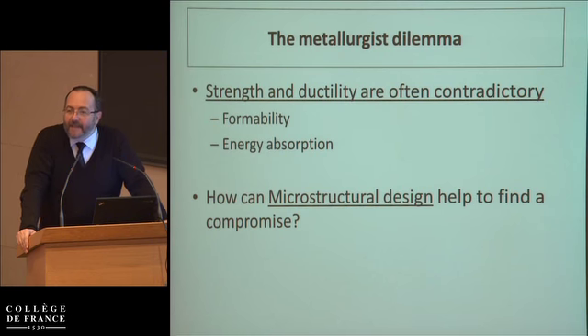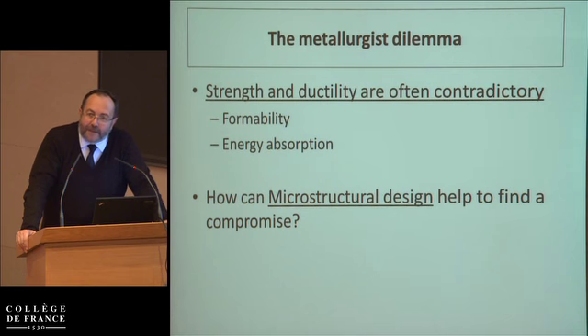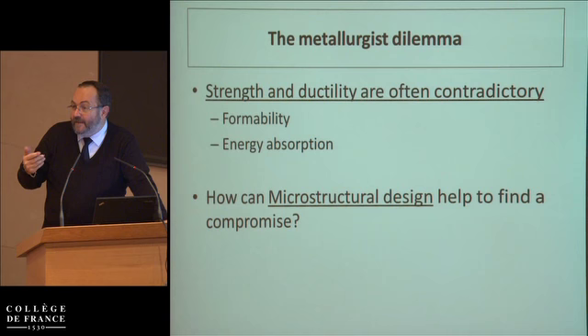Now, one way of bypassing that is to use composite material, which means to use materials which have a phase which deforms plastically and a phase which doesn't deform plastically. The net result is that you create a back stress which is giving you an apparent work hardening. So you are not changing the yield stress, you are changing the work hardening.